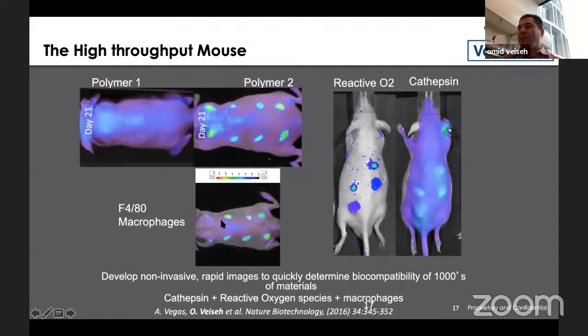And this is sort of what it looks like in practice, in that you have these materials in different spots where there's a lot of inflammation, which correlates with fibrosis outcomes, poor fibrosis outcomes. You see a lot of signal, but if the material is good, you actually don't see much signal at all. And this correlates with the kinetics and composition of the immune response in terms of macrophage and neutrophil activity.